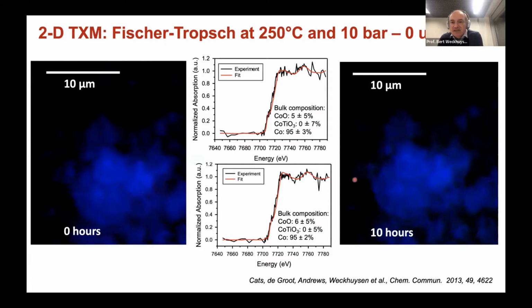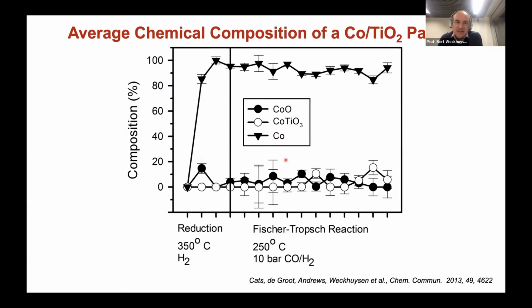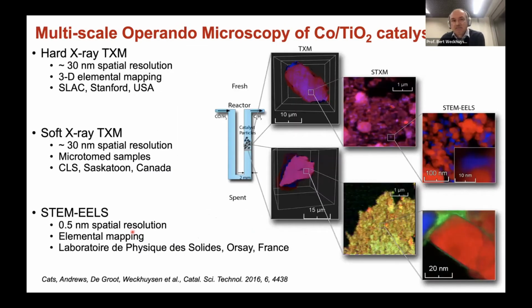0 hours of catalysis, 10 hours of catalysis, and we have been determining cobalt oxygen, cobalt titanium, cobalt metal. Hardly cobalt oxygen, hardly cobalt titania, although you can say there is some noise in it, so I'm not excluding it, mainly cobalt metal. And that is also the hypothesis in the literature. However, as I will show you, cobalt oxygen, cobalt titania, and cobalt carbide can exist.